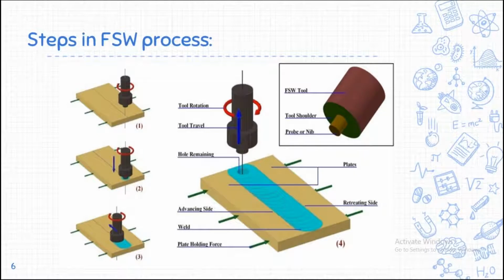For understanding, you can simply categorize this process in 4 steps. The first one is rigidly clamping the workpieces and aligning the tool at the center of the weld line. Plunging of the tool into the workpiece is the second step. Once it completely plunges, we keep it at the same place for around 25 to 30 seconds, until the required heat is generated on the workpiece. Once the required temperature is produced, we move this tool along the weld line. This is the traversing step, the third step. Once it reaches the end point, tool removal is the fourth step in the friction stir welding process.